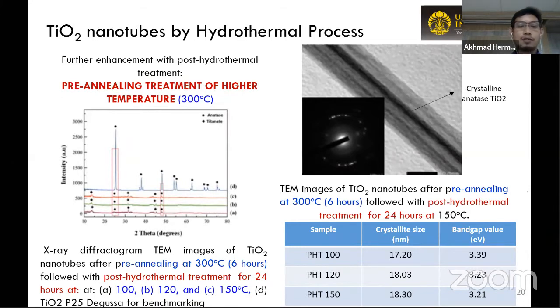We used these nanotubes for our dye-sensitized solar cell, but I'm not showing it in this presentation. We can see that the efficiency of the DSSC made with this nanotube has been improved. Of course, the efficiency is not as high as silicon-based solar cells. This is still the problem and challenge with the dye-sensitized solar cell; the efficiency is still considered quite low. But why I'm showing this example, although perovskite solar cells are now more promising, is that at least we can see the nanotubes can be made from our own local resources. That's the main message. Next slide, please.